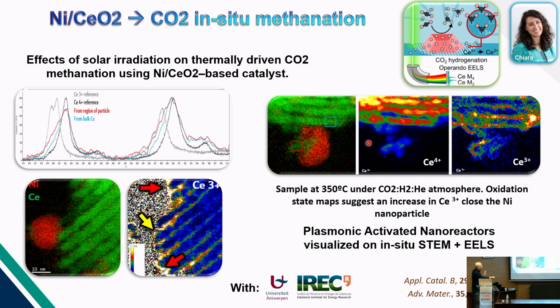But we were theorizing that the CO2 was reduced next to the nanoparticles because the plasmons from the metal nanoparticle could hit, under illumination, the surroundings of the nanoparticle, and these parts were really reduced with the hydrogen, but also the spillover of hydrogen from here.